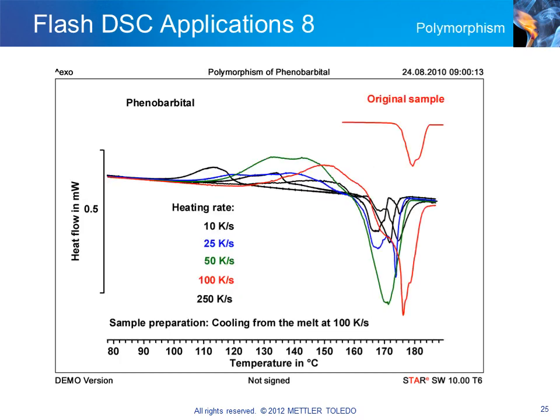The morphology of substances with different polymorphic phases depends on the thermal history, such as the cooling and heating conditions. The slide shows the complex melting behavior of phenobarbital. The original material has a melting peak at about 180 degrees Celsius. After cooling at 100 degrees per second, it is amorphous. If this sample is seeded with small needle-like crystals, different phases are formed on heating depending on the heating rate used. 6 different polymorphic phases can be recognized in the measurement curves.